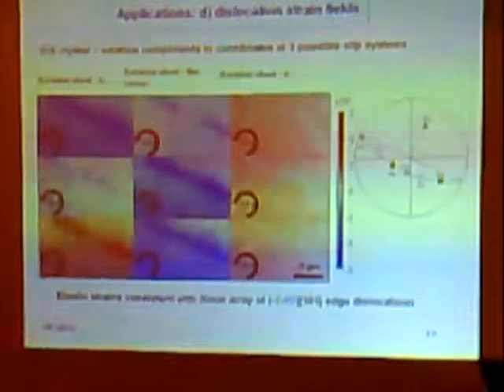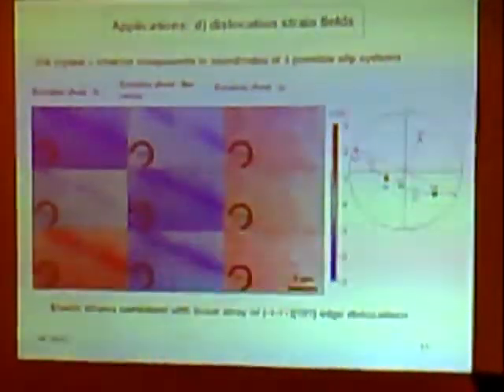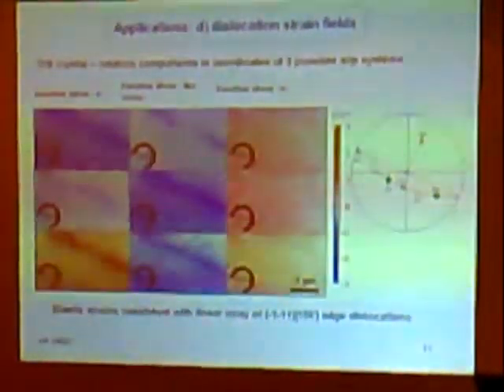What you would usually do is look at these in the sample coordinates. And the linear defect, if you look at the crystal, turns out to be parallel to a 1,1,1 slip plane trace. So the question then is, let us look at the elastic strains and rotations in the coordinates of the possible slip systems. So this is the (1,1,1) plane, it's got 3 possible Burgers vectors, [1 bar 1 0], [1 0 1 bar], and [0 1 1 bar], and this is looking at rotation about R1, about the Burgers vector, about the line vector, and rotation about N.